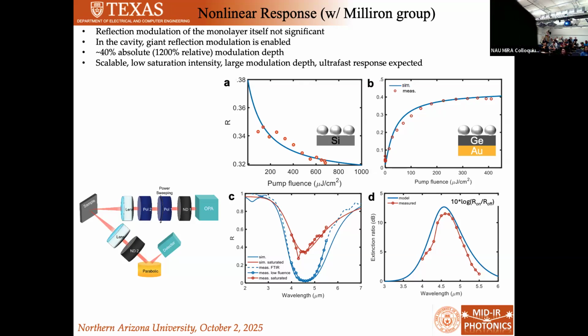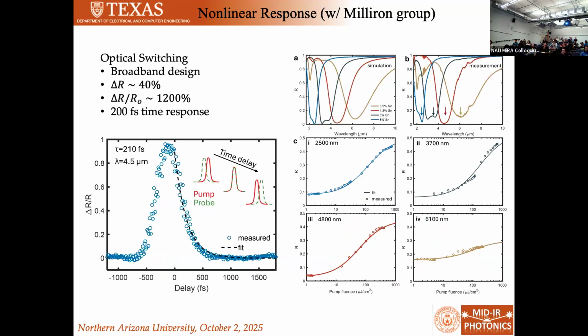But what's even cooler about this is that these are a bunch of different samples at different wavelengths under femtosecond pulse excitation. This is a pump probe measurement that actually measures the temporal response of this reflectivity change. And what you see is that the time scale associated with that change is on the order of hundreds of femtoseconds. So sub-picosecond switching. In fact, this is the limit of our measurement system. It might be faster, we don't know. Right? So this opens the door to being able to do terahertz frequency switching in the mid-IR using these really cheap large area materials. And so there's a number of applications that we're pushing on for leveraging these materials.